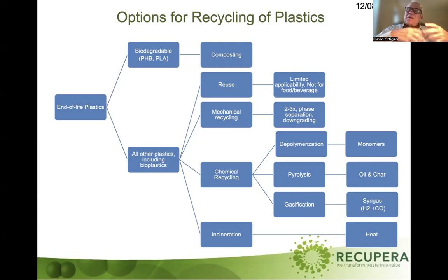It's important to note that the plastic has already been removed. It is removed from the wells, from the earth, and then made into some products. You use the product, and then you have the waste. So this is a way of taking care of the waste. And of course, you can use the energy in the plastics to drive the low temperature gasification, which is autothermal. The high temperature gasification you cannot do, because plastic does not have enough energy to sustain this high temperature. But when we reduce the temperature, we have the solution for that.